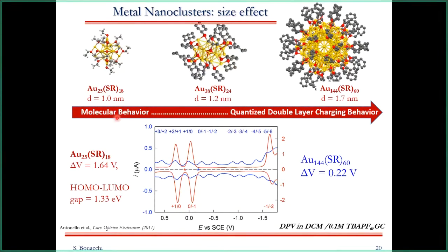And just to give you an example, if you look at the size effect, for instance, starting from the smaller gold 25 to the bigger 144 cluster, you can clearly see, and here is a result obtained in our group here in Padova, that the Au25 has a molecular behavior, with a very nice DPV curve in which you can clearly observe a well-defined HOMO-LUMO gap. Instead, as soon as you start to increase the size of this cluster up to one of the bigger ones, Au144, you lose this molecular behavior. You are going to the double layer charging behavior. So a size difference of just 0.5 to 0.7 nanometer of the diameter can dramatically change the electrochemical behavior of this cluster.